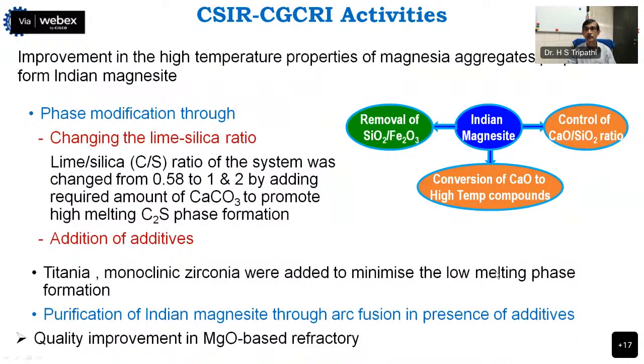At CSIR-CGCRI, we have carried out some work to improve the thermomechanical properties. So we have taken different approaches. If it is Indian magnesite, as I mentioned, if you can control the lime silica ratio, you can change the phase assemblage, and to some extent you can improve the thermomechanical properties. Or remove the CaO content, or convert the CaO to different high temperature compounds using some additives, or remove the silica and iron oxide from the component. And if only CaO is there with the magnesia, it will not deteriorate the high temperature property.